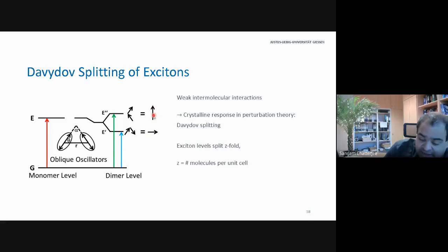If you have some insight into optical spectroscopy, you see that you can already address these using polarization-resolved spectroscopies, because if the dipole moments are oriented, then you can address them by linear polarization orthogonal to each other. In a way, the Davydov picture is a perturbation approach to a more delocalized, generalized picture. It basically says that exciton levels can split Z-fold, if Z is the number of molecules per unit cell.